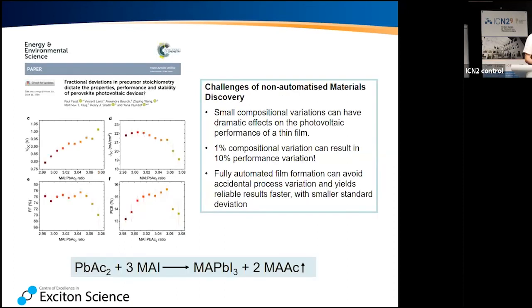This is one of my favorite slides, and my students are already smiling when they see that because I show it over and over again. It's some work from Henry Snaith's group. It's maybe a bit small to see, but they have this lead acetate reacting with methylammonium to form the perovskite. And this methylammonium acetate will evaporate off, as methylamine and acetic acid.